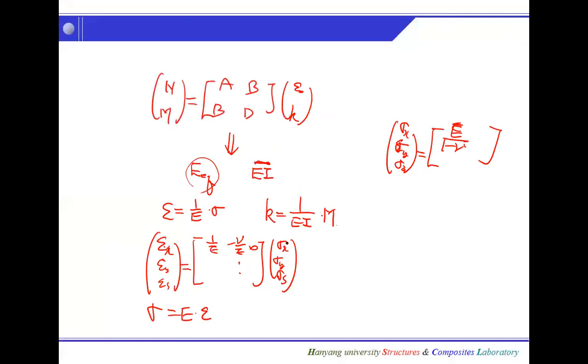The reason is that when we measure Young's modulus, we always apply stress, and the other stresses are zero. We let the material contract. So we apply the stress here, and it contracts. The stress is a certain value, and the others are zero, and that's why we got these equations. If we use this one with epsilon zero, this is the conclusion. It looks very similar but is totally different, as much as a Poisson's effect difference.